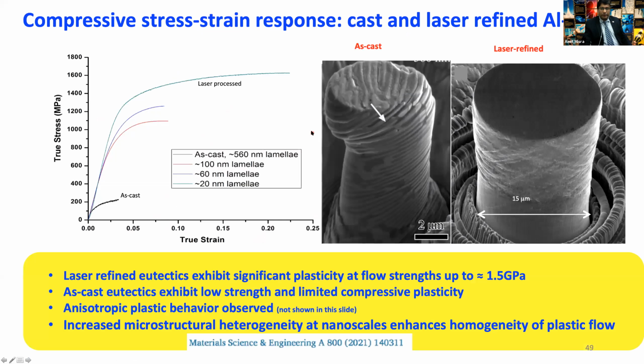And here also we see something similar, that as the structure gets finer, not only is it stronger, you get more plasticity, but more importantly, the distribution of plasticity that you can see from these very fine scale slip bands that are distributed uniformly. The plasticity gets distributed uniformly, and that is very promising, that it is suppressing these kinds of localization that we often see as the bottleneck with these high strength nanomaterials.